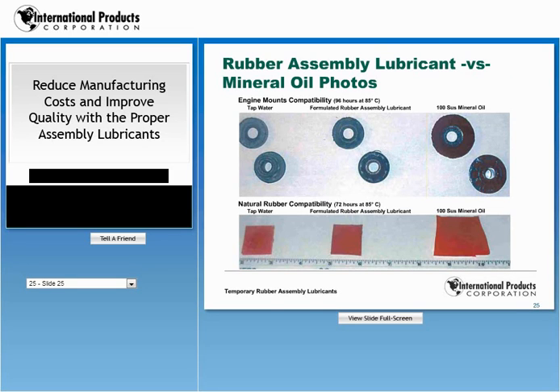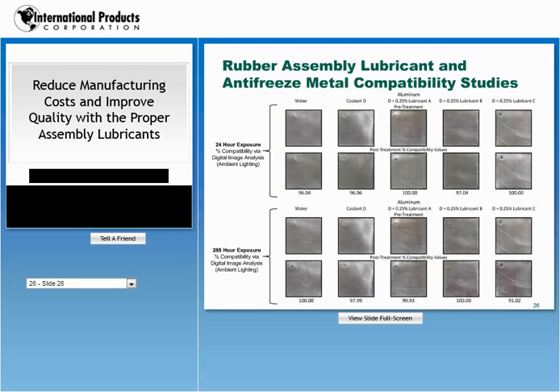Same type of analysis was done on natural rubber coupons. They were cut 1 inch by 1 inch, and again the same type of test was performed. Tap water, formulated rubber assembly lubricant, and mineral oil. Also, specific tests can be tailored to suit your needs. For example, one customer wanted to know the effect of lubricants with radiator fluid, with coolant. So a test was set up, and basically comparing any darkening that would occur with certain metals before and after exposure.